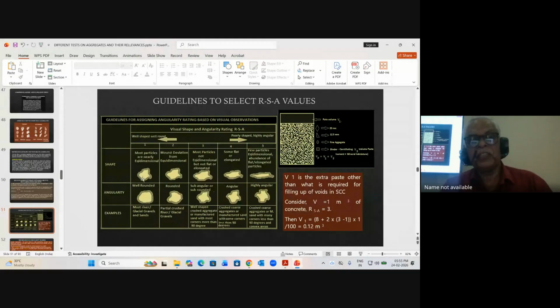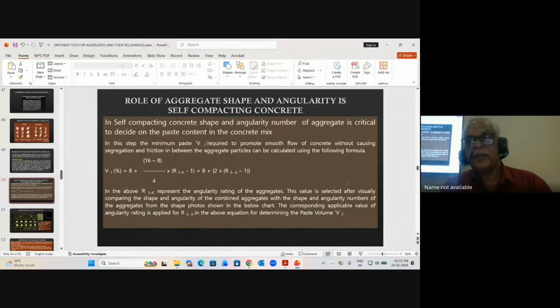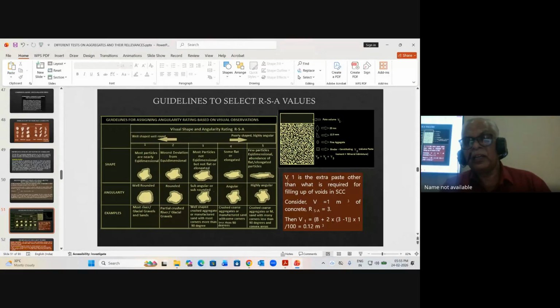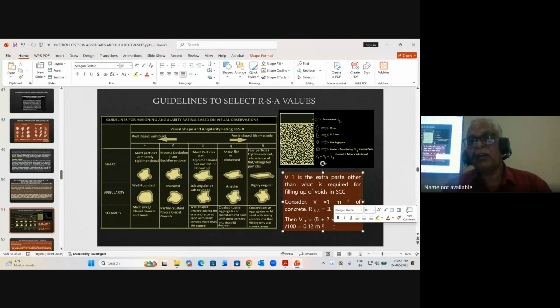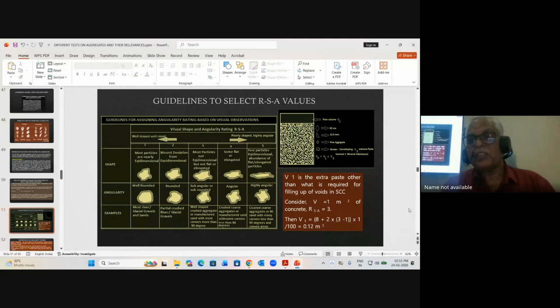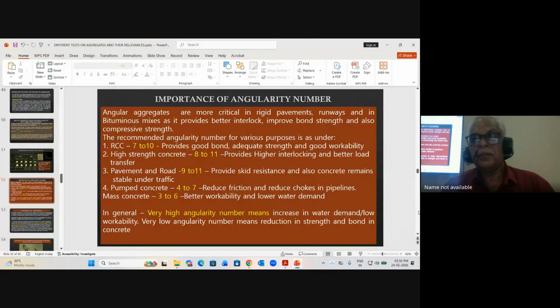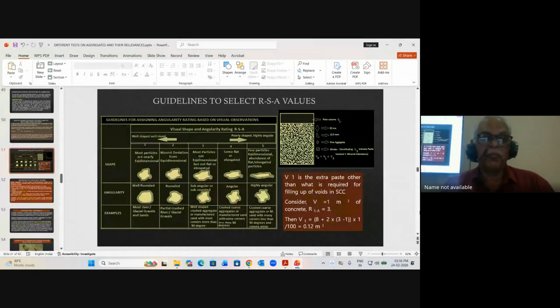If this is the typical shape, you have to take 1. If this is the one, you take 1, 2, 2, 3, 3. So from the shape you can decide this number, go back to the previous formula, apply it here, and you can see how much extra paste is required in self-compacting concrete to give a very flowable concrete. This is not given in any standards. I have taken it from some research work, and I find it very informative. I have used this in designing many self-compacting concrete mixes using these guidelines.